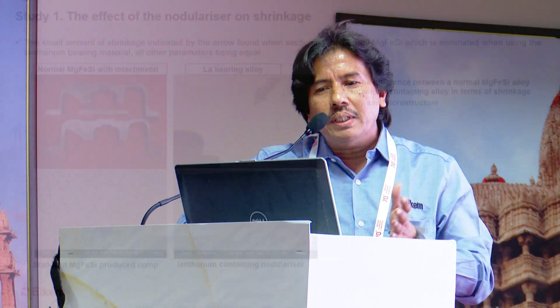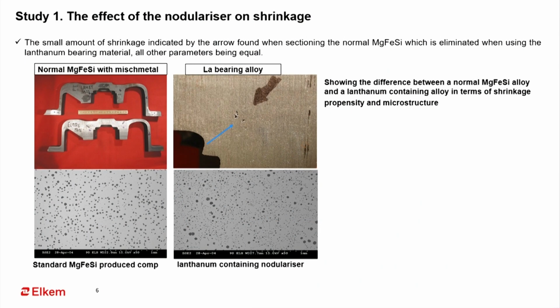So with lanthanum bearing magnesium, definitely if you compare cerium containing magnesium and lanthanum, in lanthanum you will get the highest nodule count and nodularity. Along with this, if you change this inoculation package also, definitely it will help to control the microporosity.